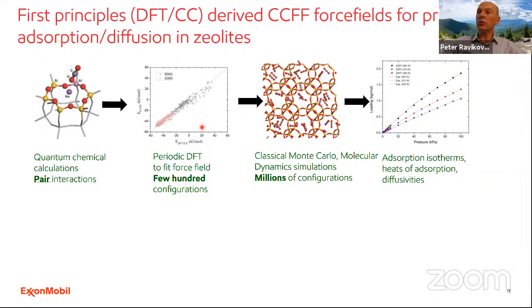But DFT is not always accurate, and you need to correct it using much more accurate quantum chemical calculations using coupled cluster methods. We use it for specific pairs of atoms. By doing this, we create the energy grid, which then can be fitted to the force field. The force field will include Coulombic and Lennard-Jones interactions. Then we can use classical Monte Carlo and molecular dynamics simulations to predict adsorption isotherms and diffusivity. So this is the overall approach.